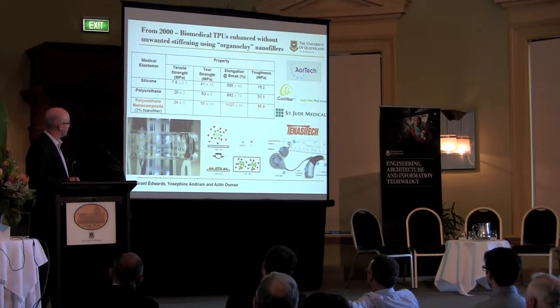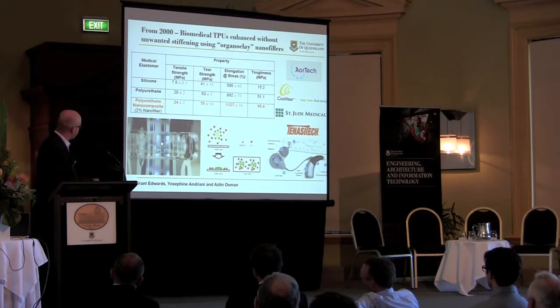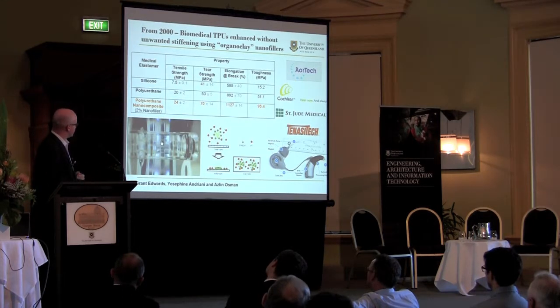We pitched to an enterprise workshop back in 2006 and eventually formed a startup company, and obviously we were protecting the technology with patents and so on. But we did a heap of work on these biomedical nanocomposite formulations, even to the extent of doing all of the toxicology. I'm not sure whether that video is linked, but we did dynamic in vitro fatigue leaching tests to measure whether the nanoparticles were coming out of the composite. We did all of the toxicity in vitro and in vivo to make sure that these organically treated nanoparticles were safe.